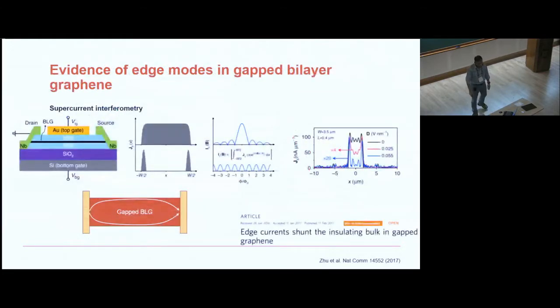The question that we asked is, okay, now forget about the internal defects, what about the edges of bilayer graphene? And recently, actually this year, the Manchester group came up and said that, okay, we put superconductors at the two edges of bilayer graphene. I apply an electric field, so I gap the bulk of the bilayer graphene like this, using two gates. There's one gate on top, there's one gate at the bottom. I apply an electric field, and the bilayer graphene is completely gapped out. Then I have two superconductors, and when Cooper pairs are injected, there's a coherence all over the system, and that leads to a supercurrent interferometry.